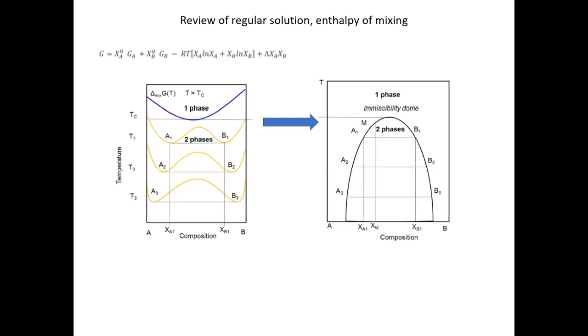That's the basic idea. And from the free energy curve, suppose we have this symmetric free energy, which again is an example. We can easily use the double tangent construction, which we've seen many times, to construct the phase diagram. Suppose this is your free energy curve at different temperatures. For each free energy curve at each temperature, we do the double tangent construction, find the equilibrium compositions of the two phases, and then map these compositions on the corresponding diagram here. We're going to construct, in this case, a solvus, which separates the mixing solid phase and the demixing solid phases. If you connect the solvus together, you're going to have this coexistence, and this phase diagram.